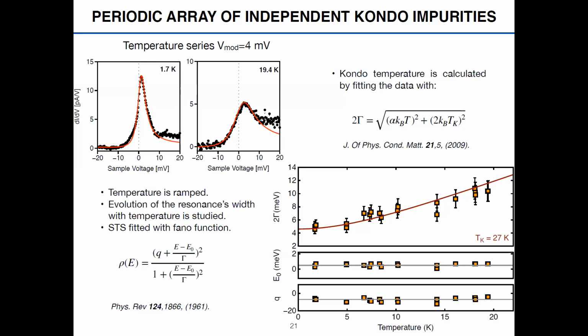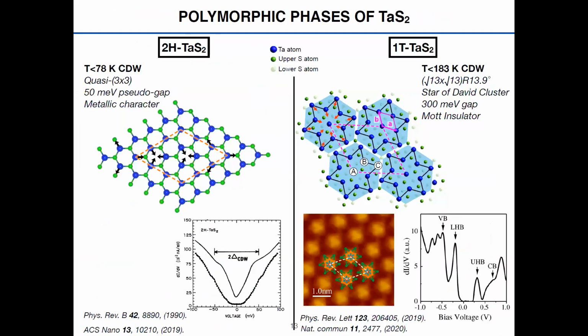No. In 2H, when this 3x3 charge density wave appears, the distortion of the lattice is very small. It's much stronger here. And actually, you have this transition to a charge density wave, but also a metal-insulator transition, which in 1T crystals is discussed. In single layers, there's more or less agreement in the literature that a 1T single layer is a metal-insulator.